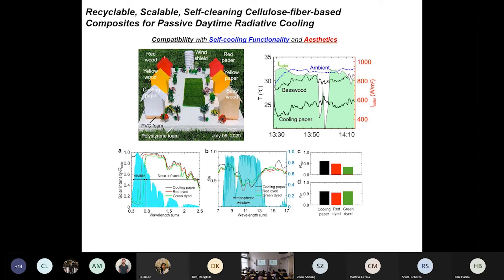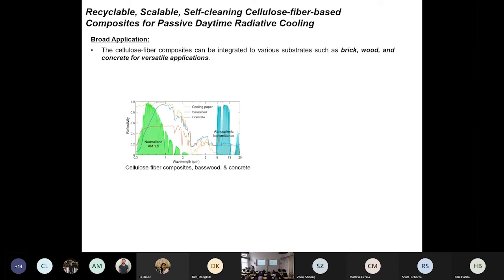So if that's the case, we have to dye the paper. We studied the dyed paper, and we found that different color dyeing does not affect the passive cooling performance much. We also measured the reflectance and the emittance for infrared light. You can see, for example, for the red dyed and the green dyed papers, this can be comparable to the white cooling paper. So we demonstrated that.